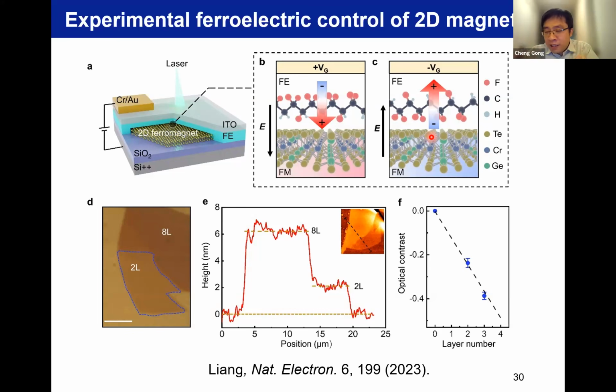Voltage is not so effective in terms of changing the crystal field, but when you apply voltage, if you count that in, it can still effectively change the crystal field to a small degree. So you certainly can have that effect, either through the electric field or through electrostatic doping. You can always control it. But there are two things: one is the efficiency, the other is whether it is non-volatile. Yeah, I see. The ferroelectric layer may help to retain the magnetic state, right? Right, that's good. Okay, thank you.